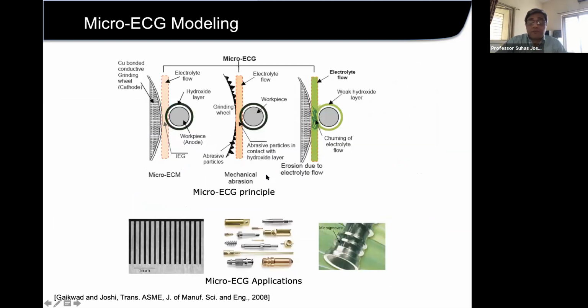At that time, another important process being considered for micro machining was the micro electrochemical grinding process. This is also a very interesting process, and primarily it is used for very fine applications like dental implants. The process is something like this: this is the grinding wheel, a conducting grinding wheel, and there is electrolyte flow, which generates a hydroxide layer on the surface. We say that this is an insulating kind of layer, and these abrasive particles abrade that insulating layer during the grinding process and expose the new surface to the flow of electrolytes so that the electrolysis process can happen.